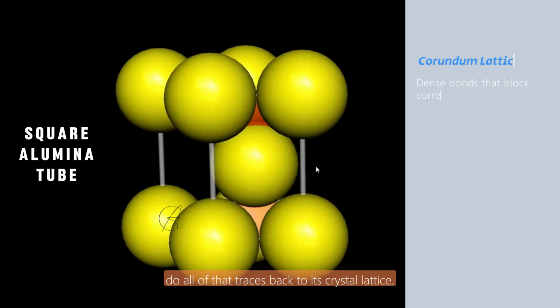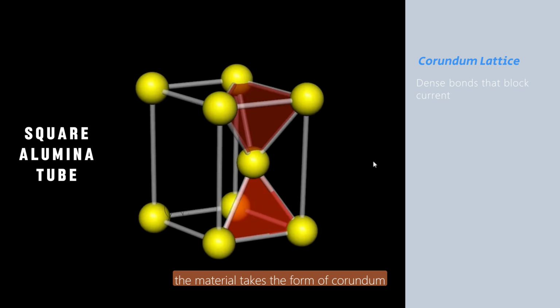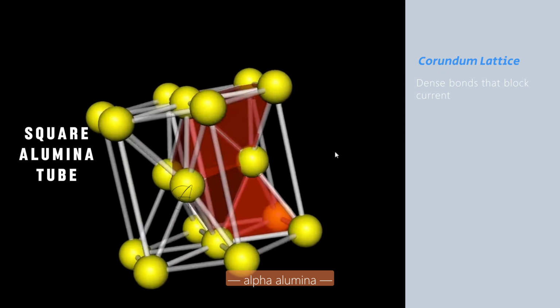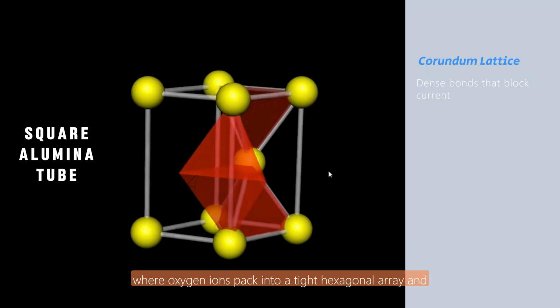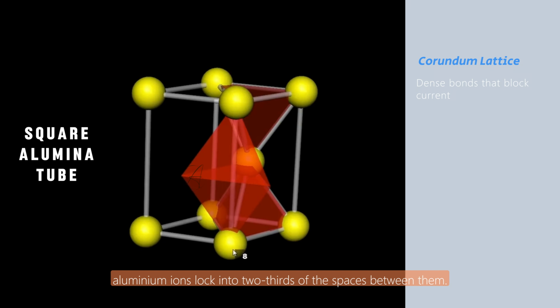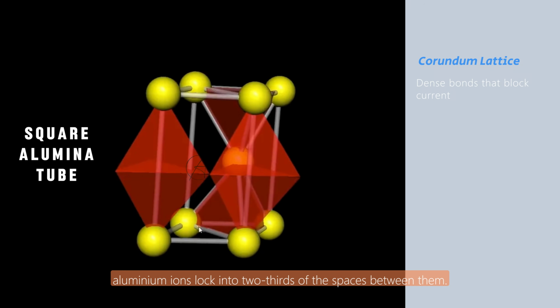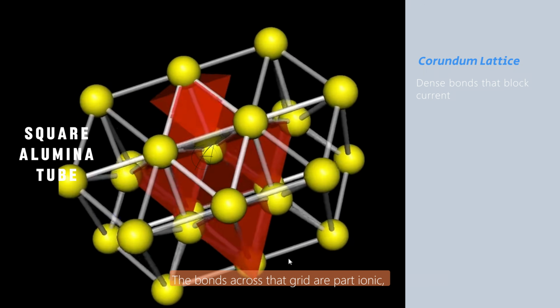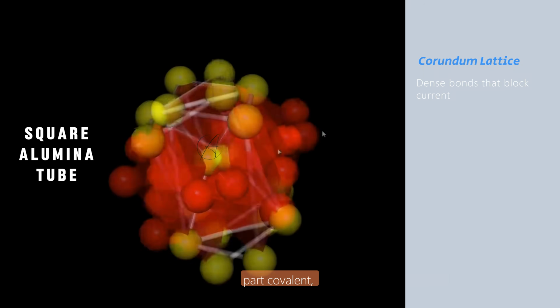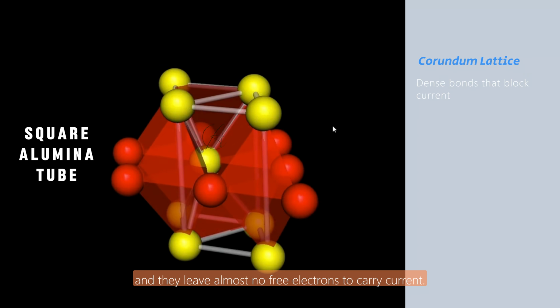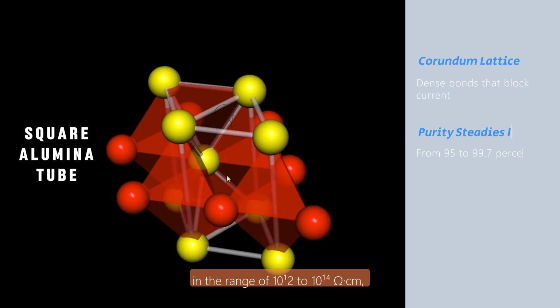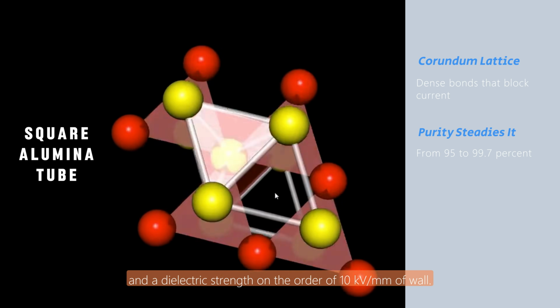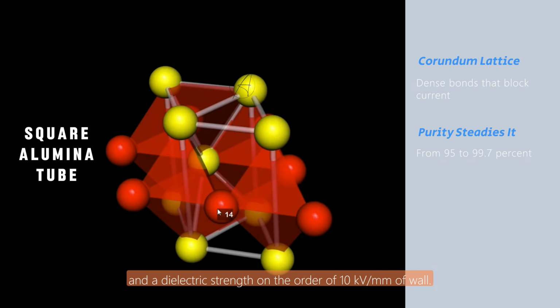The reason one fired tube can do all of that traces back to its crystal lattice. At full density, the material takes the form of corundum, alpha-alumina, where oxygen ions pack into a tight hexagonal array and aluminum ions lock into 2/3 of the spaces between them. The bonds across that grid are part ionic, part covalent, and they leave almost no free electrons to carry current. That structure gives a volume resistivity in the range of 10^12 to 10^14 ohm centimeters, and a dielectric strength on the order of 10 kilovolts per millimeter of wall.